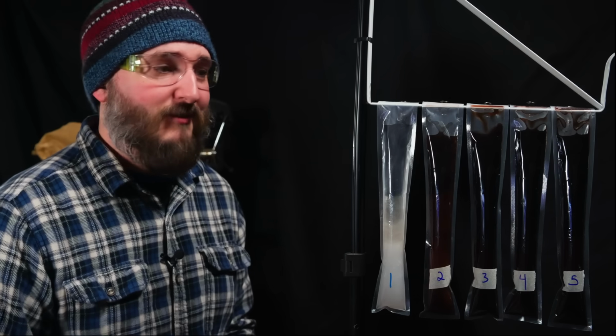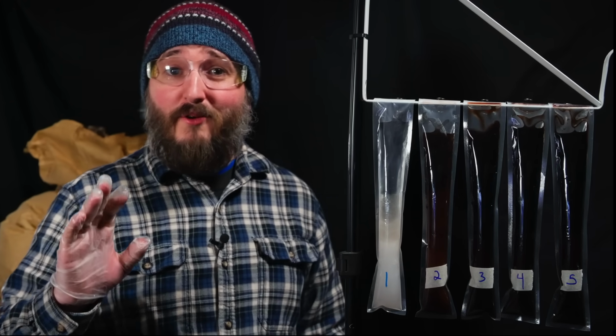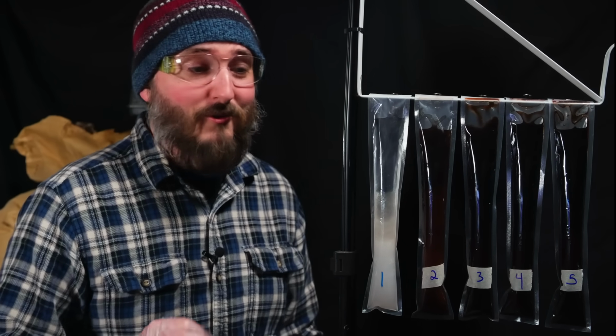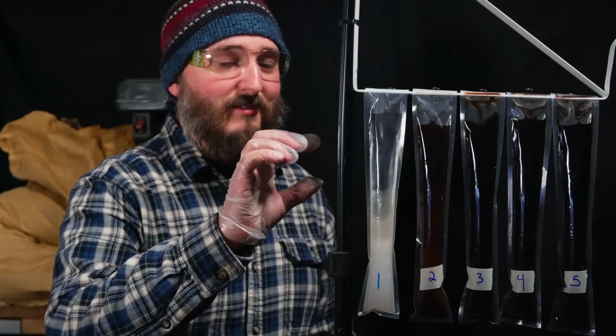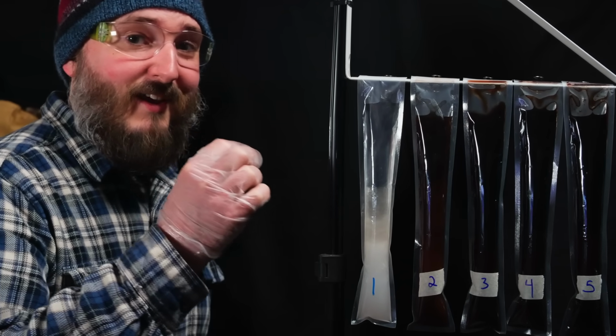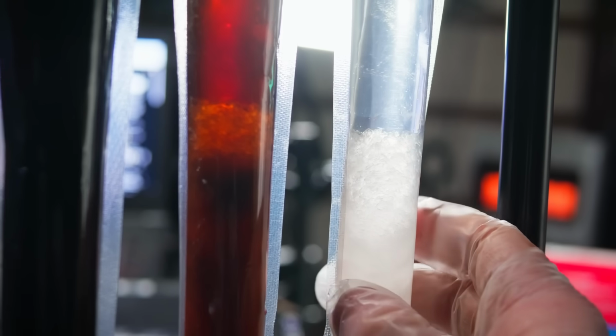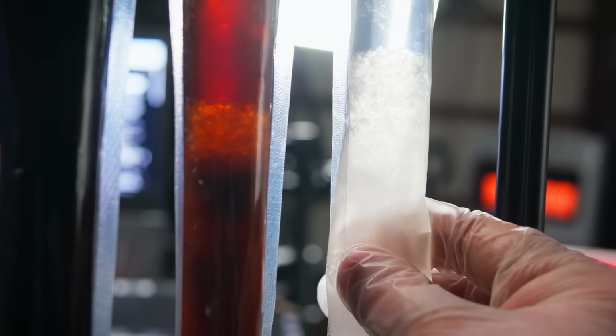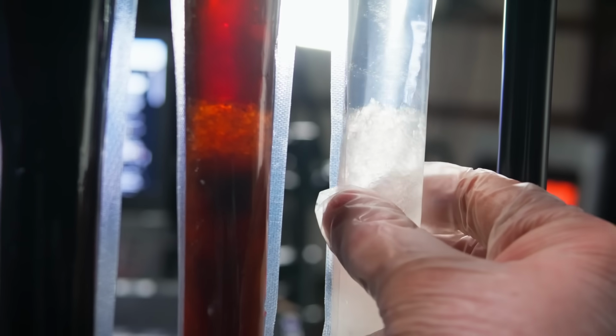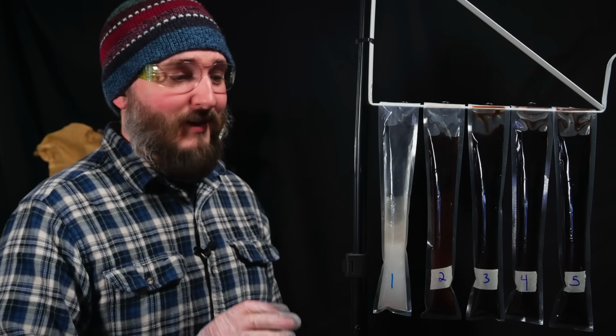So let's take a look at the results of my first series of experiments using the lignosulfonate, starting with the vertical cooldown test to inspect for sedimentation and liquid layer separation. And you can see that the control does not look good. Lots of crystals on the bottom, basically nothing homogeneous about it. There was no thickener at all in this sample, so it is not unexpected for it to have done this badly. Actually, I need to fix a problem with all of these before I can get into the results properly.